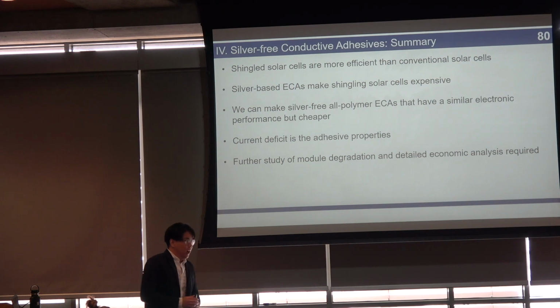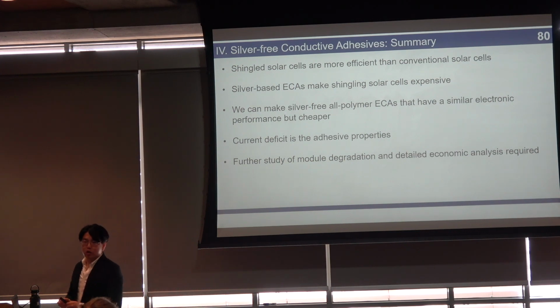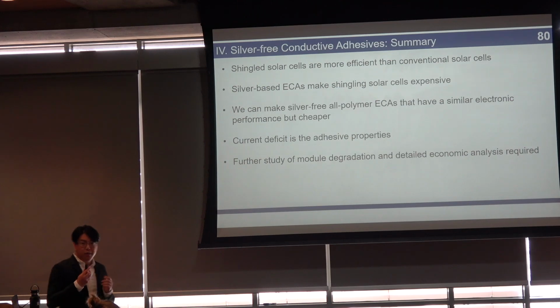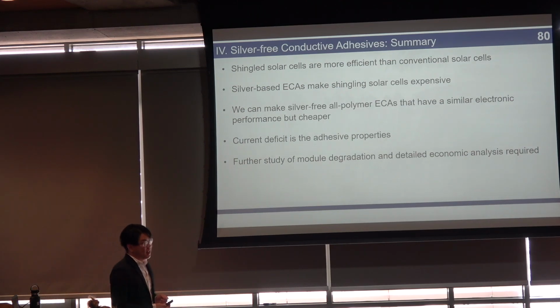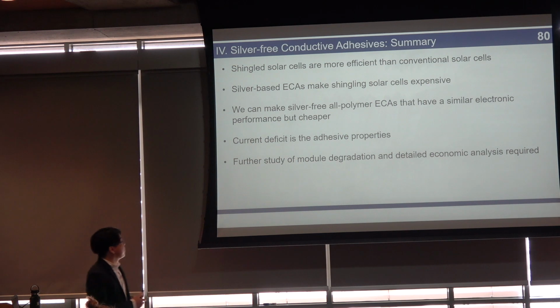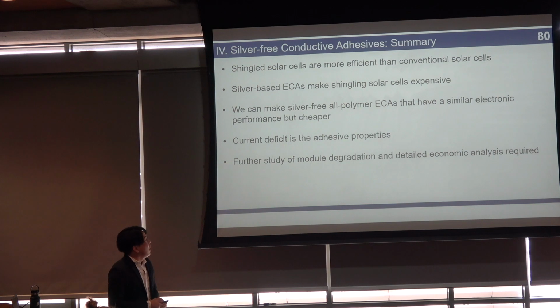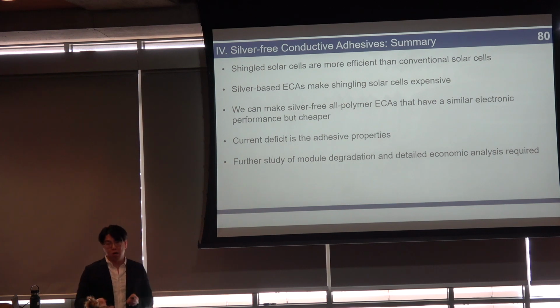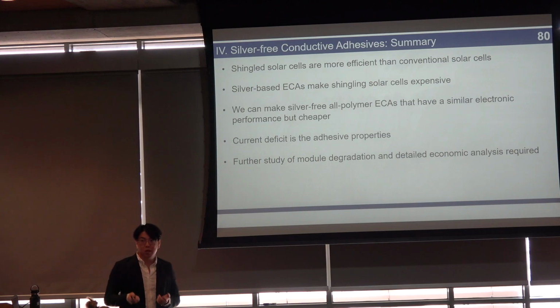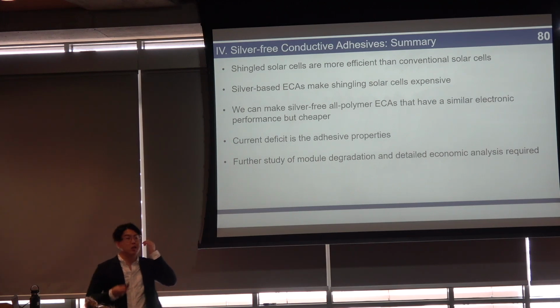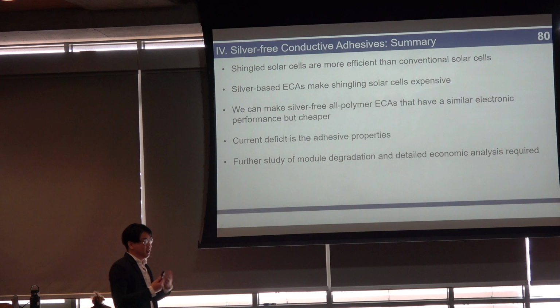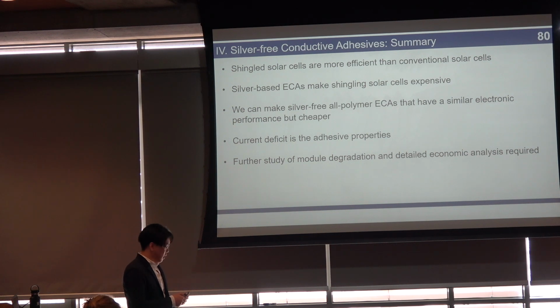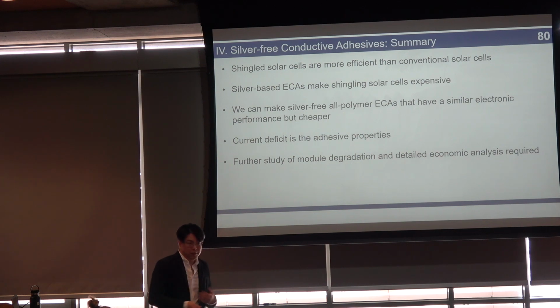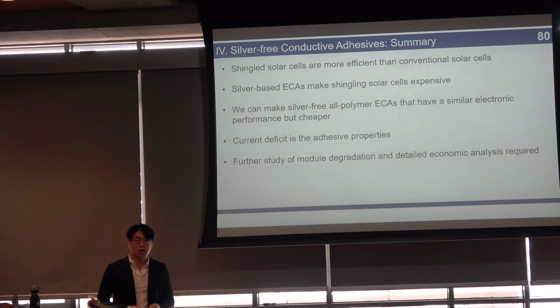So just to quickly summarize, we have conventional silicon solar cells that are already very good, but one way to make them better is to shingle them together like rooftop shingles. And instead of using silver-based conductive adhesives, we can make all polymer conductive adhesives that have a similar electronic performance, but are way, way cheaper. So that presents a potential avenue for actual commercialized products. The current deficit with these materials is their adhesive properties, which is something that we're working on right now.